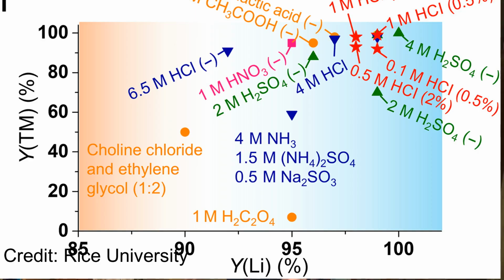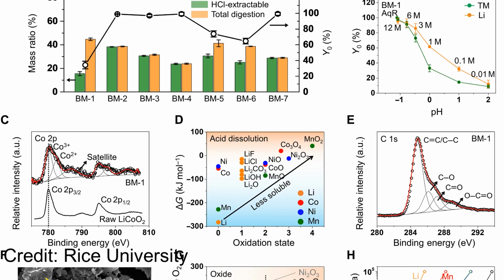And the fact is, results matter. The team reports that graphite, cobalt, and lithium can all be collected with high yield. The paper shows about 85 to 97% yields on the key materials and about 99% purity on them.